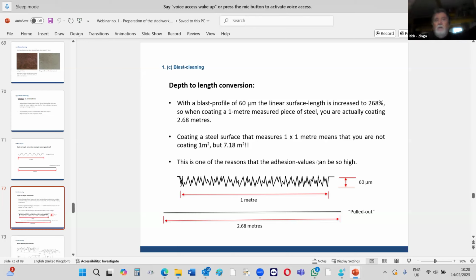So, for example, if you have a square panel of steel, 1 meter by 1 meter, and you blast clean it, when you coat it, you are not coating 1 square meter of steel. You're actually coating 7.1 square meters. So the zinc is actually sticking to 7 square meters. And this is why when you try to pull it off, it's physically impossible.